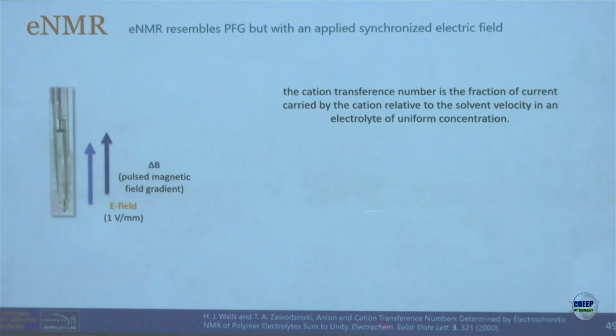Walls, which said that you can determine transference numbers by NMR. In this NMR tube, you put 2 electrodes, in this case platinum. You apply electric fields and magnetic fields. You do an NMR experiment, like a PFG NMR experiment. But what you do is you measure, as a function of the applied field, the velocities of species.